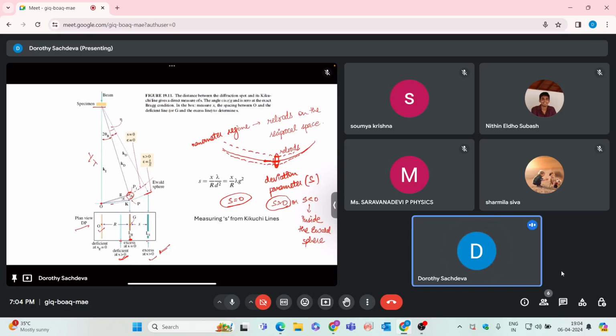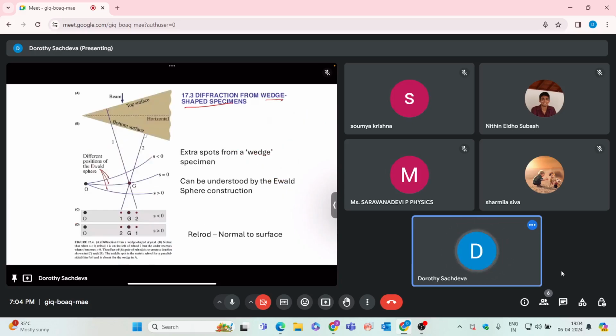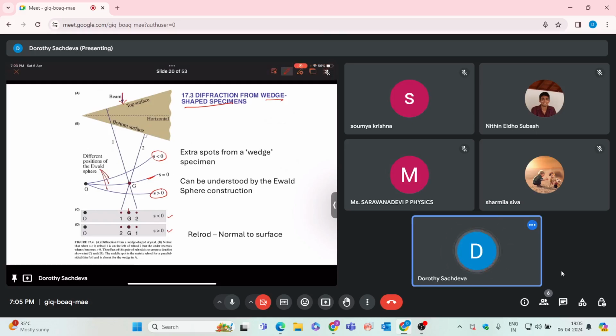So similarly, we have shown in this case, suppose the wedge-shaped specimen is there, this one in figure A, where your beam is going in this direction, and then you have your S equal to 0 like this, and then inwards your S is negative, and outside the Ewald sphere your S is positive. So then your specimen is giving, after this direct spot, excess and deficient lines both when S is negative and when S is positive. So these will tell you about the Kikuchi lines from S greater than 0 as well as from S less than 0. And I have already told you that the relrods are basically always normal to the surface. Suppose this is your sheet, then your relrods will be in this direction.